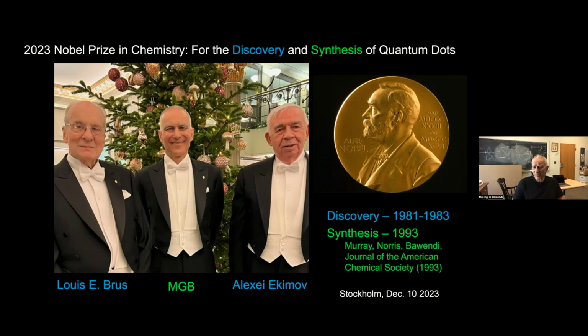Where do I come in? Well, I was a postdoc with Louis in the late 1980s. And the particles that we were working with were not particularly good in the sense that they were not crystalline, they were misshapen, they were made in water. And these semiconductors really actually don't like water very much. They oxidize. And so instead of having, say, cadmium selenide, after a little bit in the presence of water you'd have cadmium oxide, not exactly what you want to study.